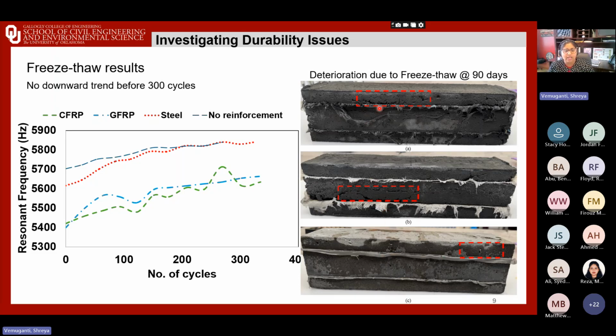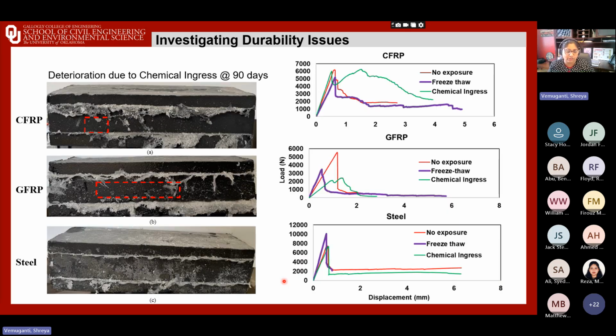and delamination. Some along the interfaces, some initiating from the interfaces, but these damages exactly show us how a freeze-thaw environment physically affected these specimens. We stopped at 300 cycles because there was no downward trend, and we basically halted the freeze and thaw and then proceeded to testing. So first, looking at the left side, now this is chemical ingress.